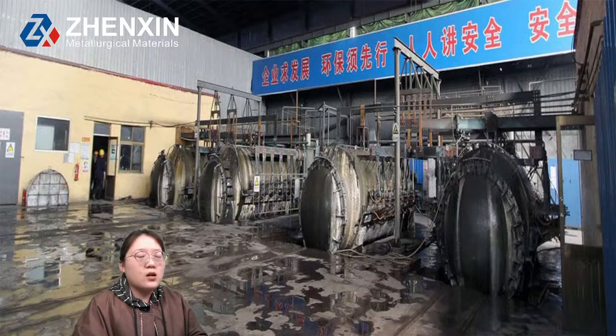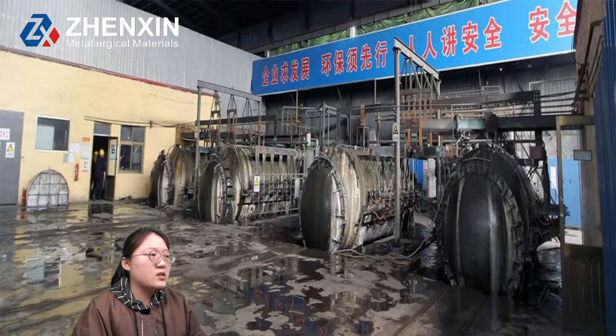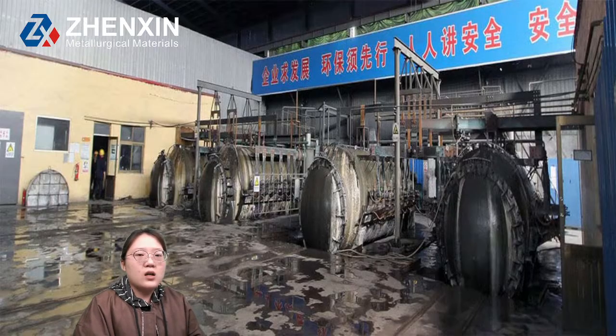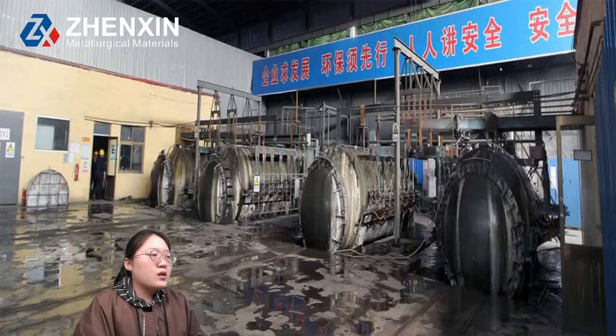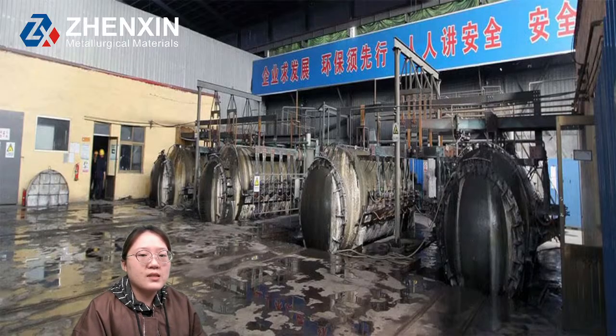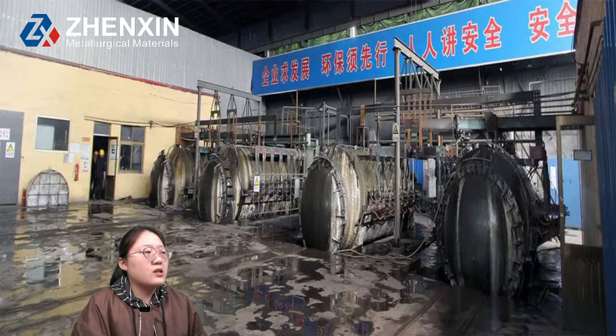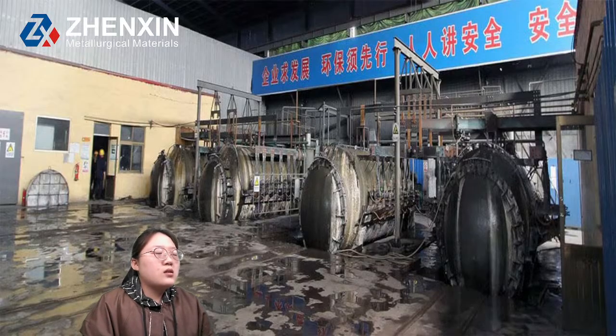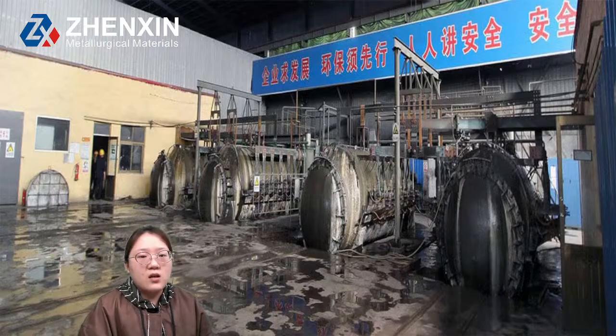Let me give an example. The chrome is higher than 60%. The nitrogen content is higher than 3%, 3 to 4% is okay, and the carbon content is just like the low carbon ferrochrome.